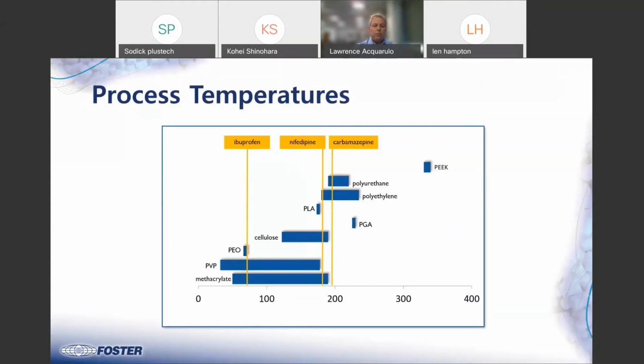If you can see the temperature profile of where these polymers process, like PLA, PGA, polyethylene oxide, those are more pharmaceutical polymers to the left, but you're looking at polyurethane, polyethylene, and even PEEK all the way to the right. You wouldn't try and melt a drug into PEEK. It would just destroy it at that temperature. But there are certain polymers and certain drugs like ibuprofen, pain reliever, very common. Nifedipine. These are model drugs that you would use to see if you can develop a product, because these drugs are available. Nifedipine, that's a high blood pressure medication.